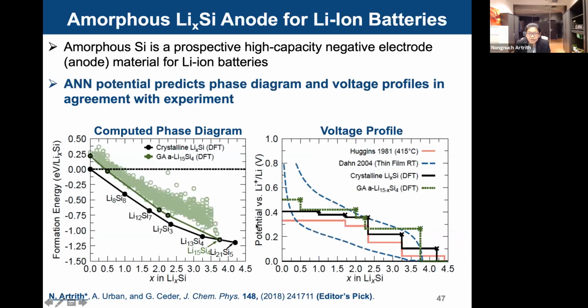Another example, you can see amorphous silicon anode that I show here. This works together with the Ceder group, Professor Ceder. In general, the silicon anode is a really challenging system to model because of the amorphous silicon alloy phases. So we train neural potentials to reproduce silicon and lithium silicon across its crystal structures here, and also amorphous here when the battery is cycling. So we remove lithium atoms and then see how the structure looks.